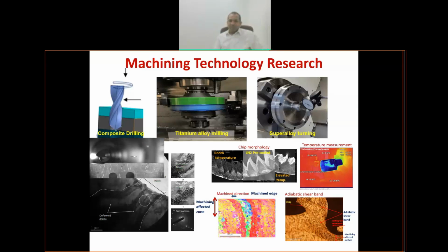Now, I know you guys must not have done a lot of stress strain, but I think stress and strain is something which you're aware of. So in machining, the strains can be as high as 800 to 900%. So you could have 8 to 9 times the deformation of the size of a material. So it can go to 800% strain. So essentially, you have a very high strain rate process, which is also going through a very large energy production.